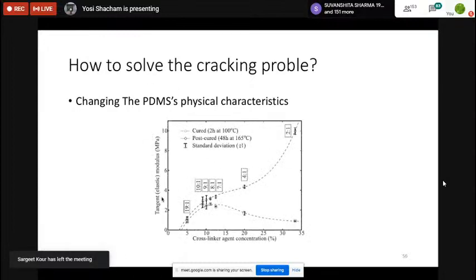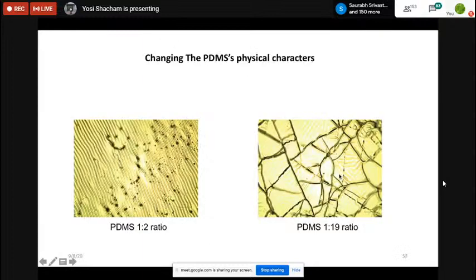So we looked at the modulus of PDMS as a function of the crosslinker. Remember how we make this polymer. We take a crosslinker, mix it with the monomer, heat it, and wait. And we look at this table and we saw, well, we can control the Young's modulus of the polymer between 1 and 10 megapascal by controlling the crosslinker. And let's see what happens. Surprisingly, when we do a 1 to 2 ratio, no cracks. We still have wrinkles, but no cracks. At 1 to 19 ratio, we got beautiful cracks.